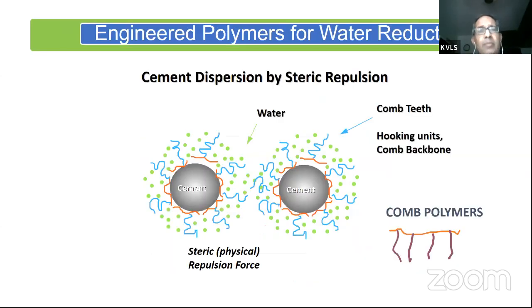Now, these polymers and these water reducers, these are chemical admixtures, and these are very highly engineered chemicals. In fact, the chemistry of these molecules is very, very complex. These are engineered. They're basically made up of these comb polymers with these teeth, and the specific composition of the teeth and the comb, the spine, these are all engineered so that I can achieve dispersion of cement paste very easily by steric hindrance that is created by these molecules. And these are very, very complex molecules that are specifically engineered.